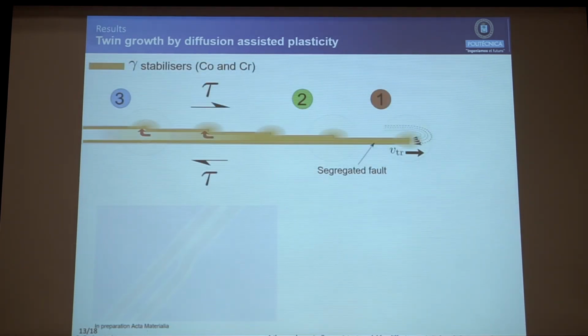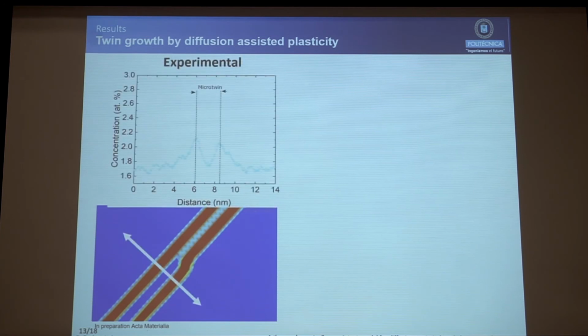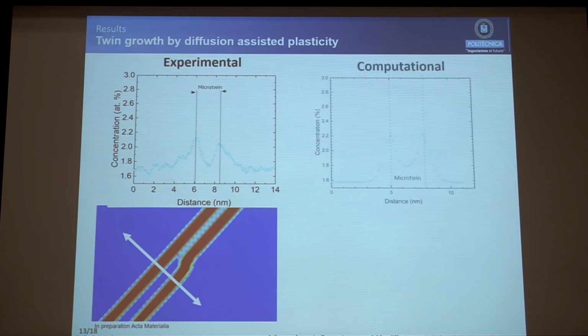So we have compared that with some of the results of the experiment. This is taken by TEM EDX, and when you make the same plot on the computational model, you get the same kind of concentration peak levels. I have to say that for the chemical part, there are no calibration parameters. Everything is taken basically from Thermo-Calc and concentration from the experiments. On the mechanical part, of course, there are calibration parameters that I have calibrated before in the previous slides.